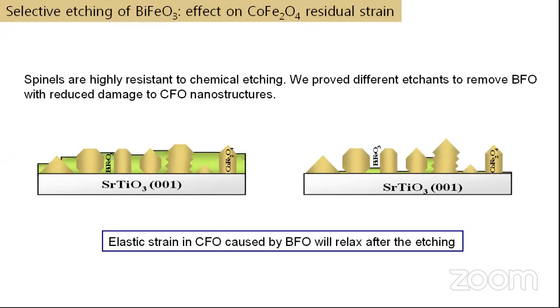As I said before, in this structure we have two types of crystal structures. One is a spinel, and another one is perovskite. And spinels are highly resistant to chemical etching. So we tried to chemically etch the perovskite part, and then see how the elastic strain was on the cobalt ferrite part. After etching, we were expecting that almost all the bismuth ferrite perovskite matrix would be removed, so you will be having only the cobalt ferrite material. So this is the experiment we tried.